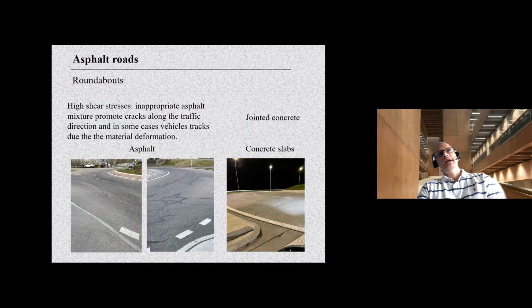One of the main issues was also the deformability of this asphalt material, so that when they put roundabouts in the streets, shear stresses are highly present, and they tend to form quite a lot of cracks, as you can see on the left pictures. And also the vehicles leave some track in the material because the material is deformed. And so sometimes they construct these roundabouts, these round circles, with concrete slabs that are jointed because of the high rigidity of the material.